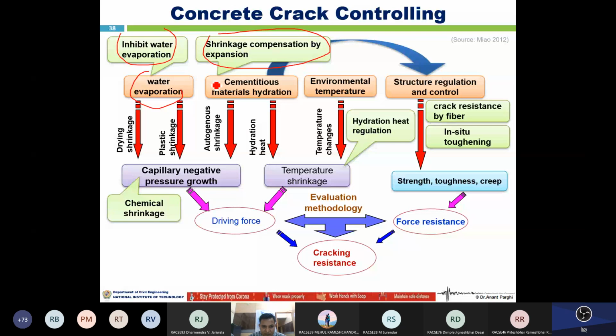This way we can stop or control the cracking, like cracking resistance, where the driving force has to be balanced by resistance, like capillary negative pressure and temperature shrinkage, which is related to the heat of hydration. If you are doing mass concreting, there is a lot of exothermic process and heat will be generated. If you are using the normal process, the heat will not be neutralized. In that case, we should use ice in the concrete. This way we can neutralize the heat of hydration.